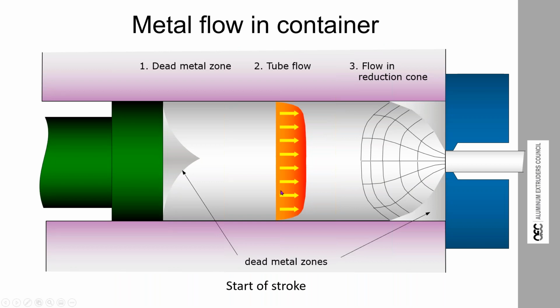The container temperature is also very important in the metal flow. When we have a great big long billet, we have metal that is stuck to the side of the container, and we are pushing aluminum over aluminum. Subject for another day, it's a long discussion, but aluminum never slides over steel. Aluminum sticks to steel, and then aluminum slides over the aluminum that is stuck to the steel. If aluminum rubbed on the steel, we would wear away the steel in no time at all. Very strong chemical attack if that happens.